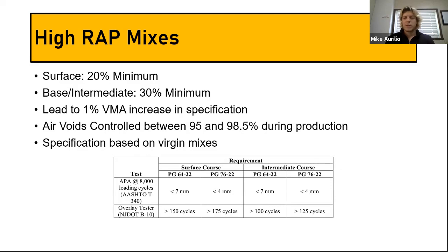So their surface courses contain a minimum of 20%, and their base courses contain a minimum of 30%. Through their research into their database, and comparing RAP mixes to virgin mixes, they found that they needed to increase their VMA specification by 1% for these mixes. They also control the air voids a little bit more tightly.